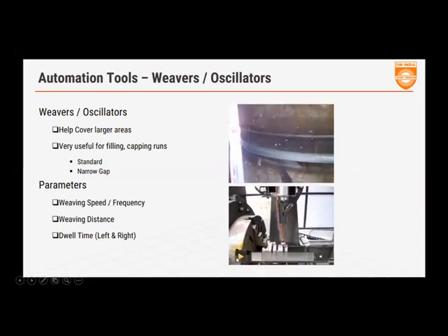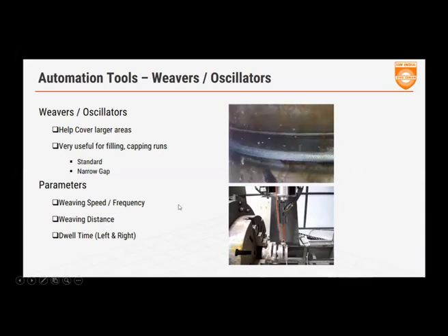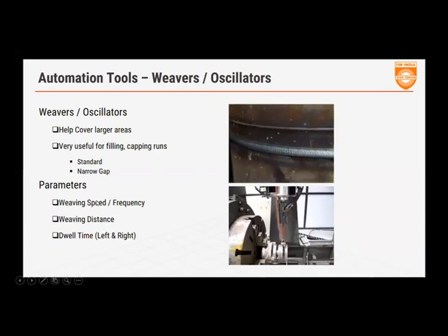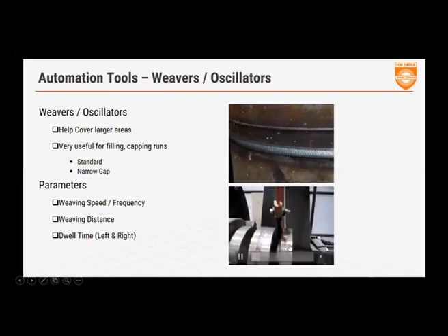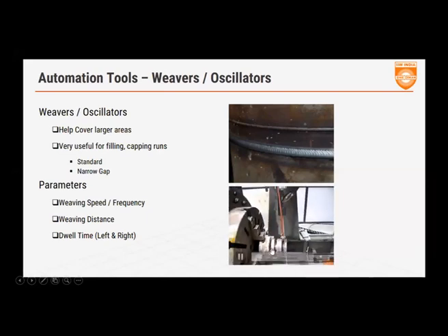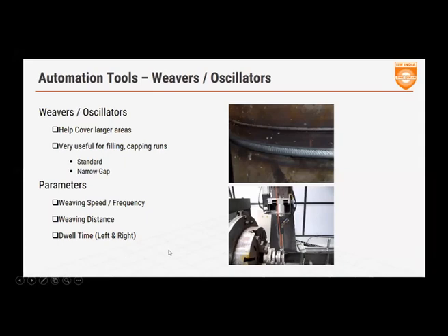You need to set the weaving speed or frequency at which you want to weave. You could set the weaving distance, what is the bead width you wanted. And very important is the dwell time. So the dwell time allows you to avoid the lack of fusion on the sides. So if you see when the torch is moving on either side, it's pausing for a second or so. That pause is nothing but the dwell time. It's settable on both left and right, and this ensures you don't have LOFs while you are welding on narrow grooves, or even when you're doing the multi-layer welds.